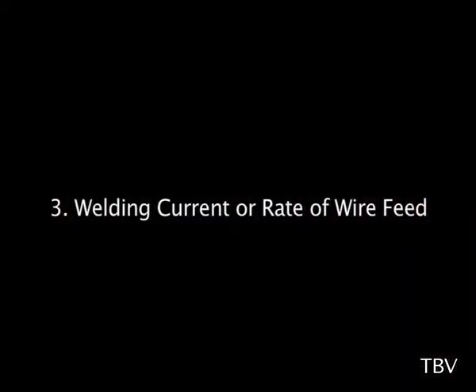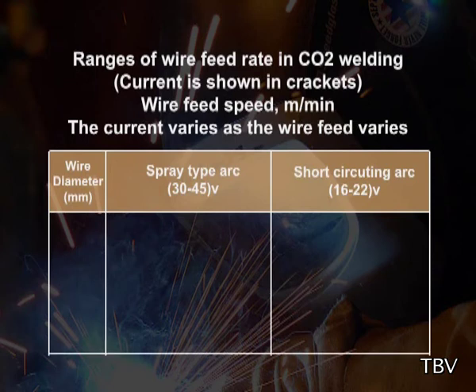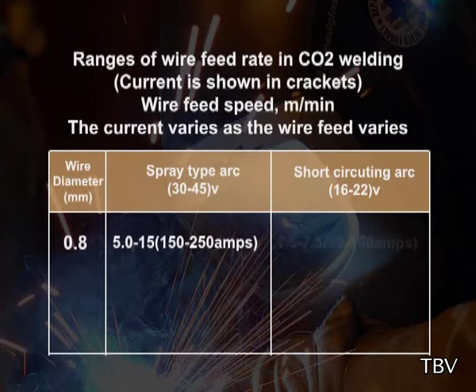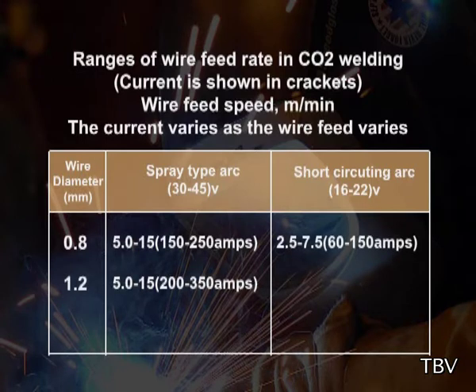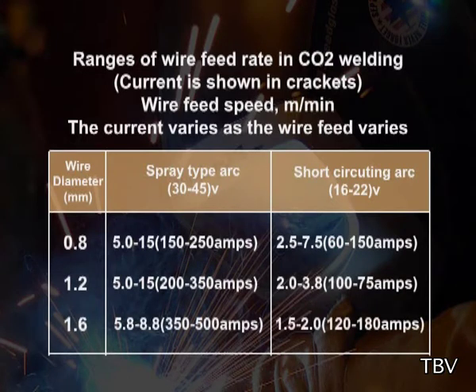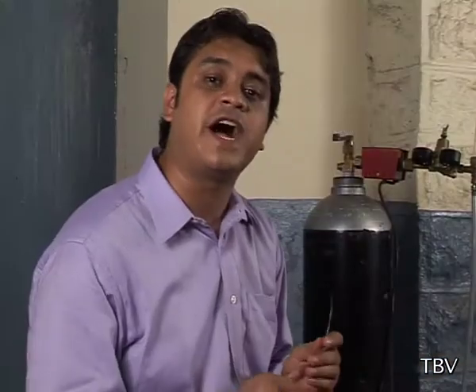Welding current or rate of wire feed. The wire feed speed will control the current. A wide range of current values can be used with each wire diameter. This permits the welding of metal at various thicknesses without having to change the wire diameter. The current selected should be high enough to achieve the desired penetration and low enough to avoid undercutting and burn through. The success of CO2 welding is due to the concentration of high current density at the electrode tip.